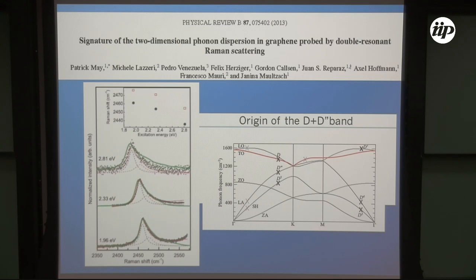However, the experimental work was done mainly by Patrick May. At the time, he was a PhD student in Janina Maultzsch's group in Berlin, I think it's Berlin. The first thing that Pedro did was measure with a larger laser energy than the people at MIT had used. And then you see experimentally, first, you have two sub-peaks. That's okay. And experimentally, they are both dispersive. That's a fact: you have two sub-peaks, and they are both dispersive. Now we propose the origin of those peaks.